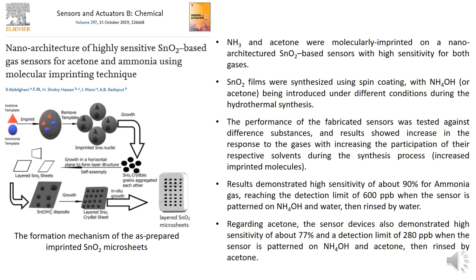This sensor showed a very good performance. As a result, it demonstrated high sensitivity of about 90% for ammonia, and the detection limit was as low as 600 parts per billion. While for acetone, the sensor device demonstrated high sensitivity of about 77% with a detection limit of 280 parts per billion.